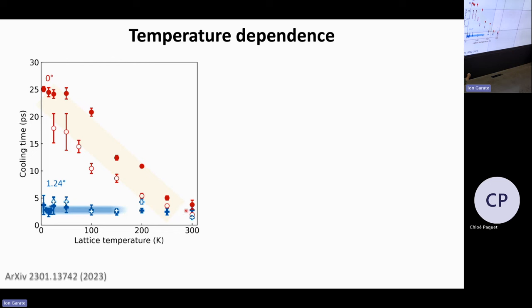But then once you start cooling down, the normal non-twisted graphene starts cooling down more and more slowly. This is because these electrons cool down by giving their energy to phonons, acoustic phonons, optical phonons. And of course, when you cool down the system, there's a lower population of these phonons. So it's more difficult to transfer this energy to these phonons. So cooling through electron-phonon interactions becomes more slow.